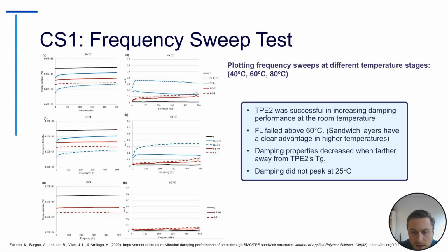The free layer structures failed above 60 degrees, and this was something they suspected with the viscoelastic layer being susceptible to environmental conditions, showing that the sandwich structures had a clear advantage in higher temperatures.